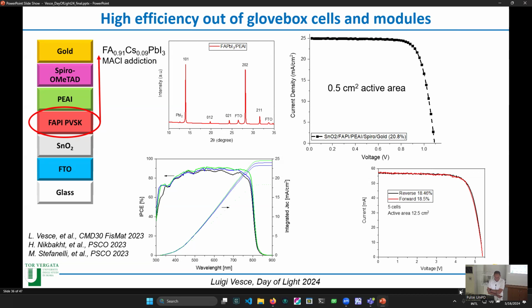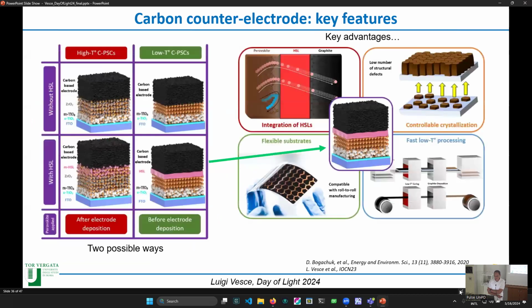Okay, but from the life cycle assessment, something is missing, no? We saw that we still have gold in our stack. We still have gold, so we have to remove gold. And one option in the perovskite field, that comes also from dye-sensitized solar cells, is to substitute the metal counterelectrode with a carbon counterelectrode. You have two options mainly. That is the high temperature or low temperature concept.